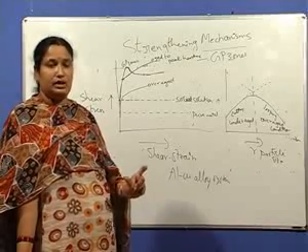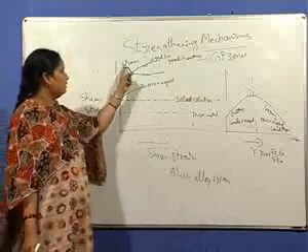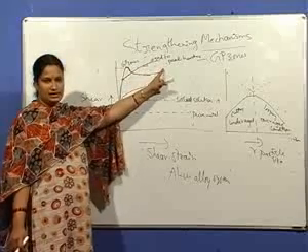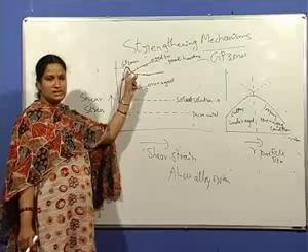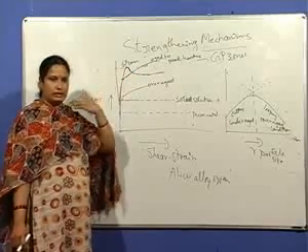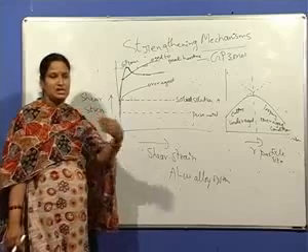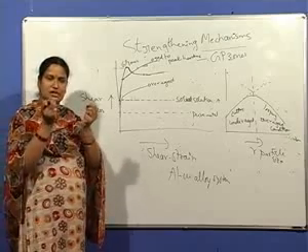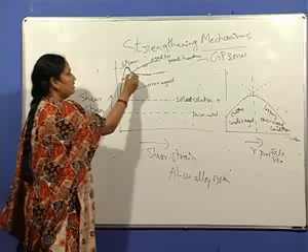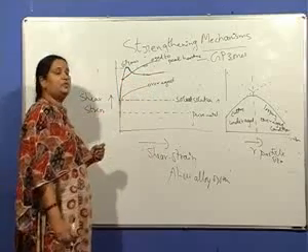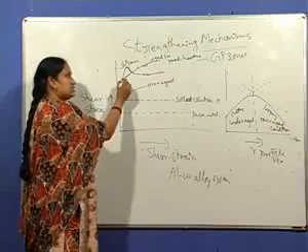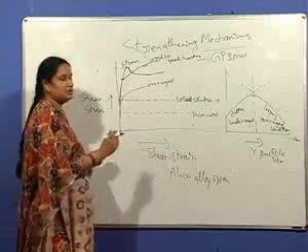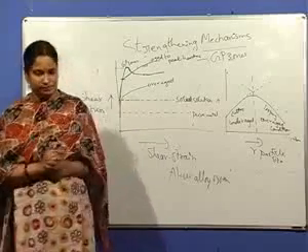The cutting mechanism requires more stress, thereby there is an increase in yield stress when compared to the alloy aged to peak hardness. Once the cutting mechanism starts, these particles are sheared by the dislocations, and the shearable precipitates become still finer and finer. Thereby, the rate of strain hardening is lower. But for the case of the looping mechanism, the yield stress is lower than for the GP zones, that is, when it is aged to peak hardness, but the rate of strain hardening is very high.